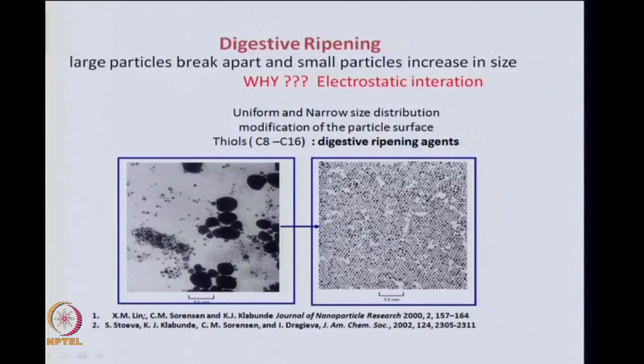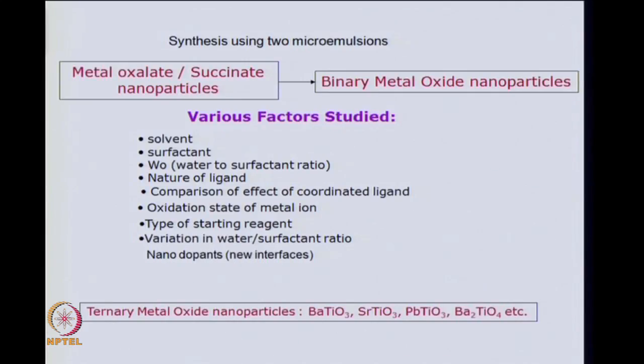And you get a very uniform homogeneous distribution of particles of very small size through this digestive ripening process. This process is not thermodynamically driven, it is kinetically driven, and this process is helped by the presence of molecules like thiols, which act as digestive ripening agents. And this kind of work has been shown in the literature by Klabunde et al. And these are some of the publications where details of the digestive ripening process, the kinetically driven process is explained in detail.